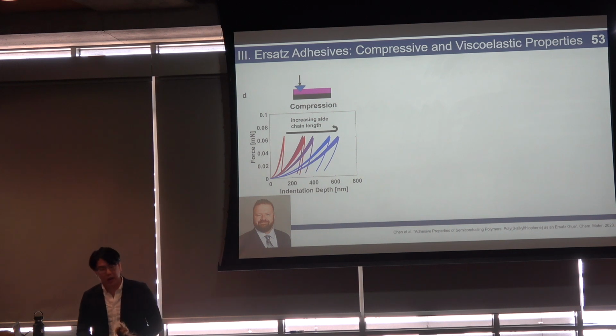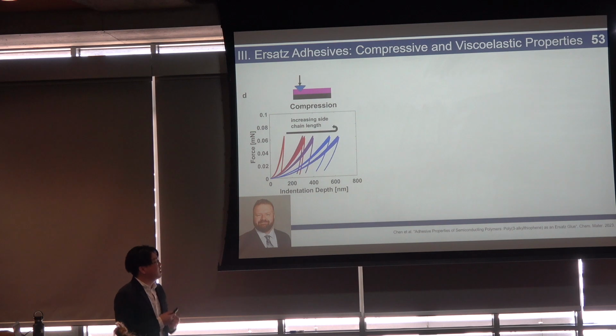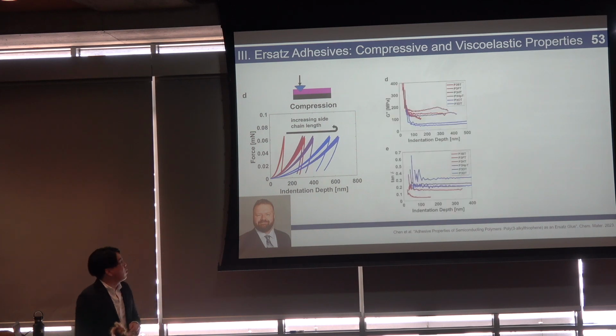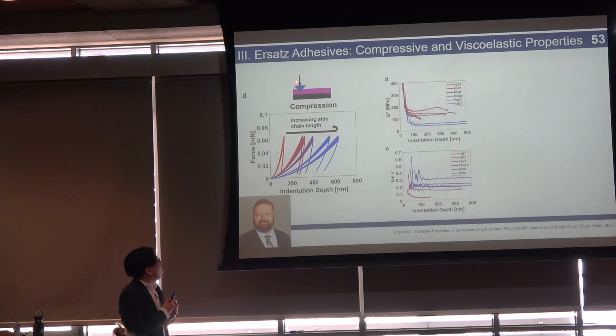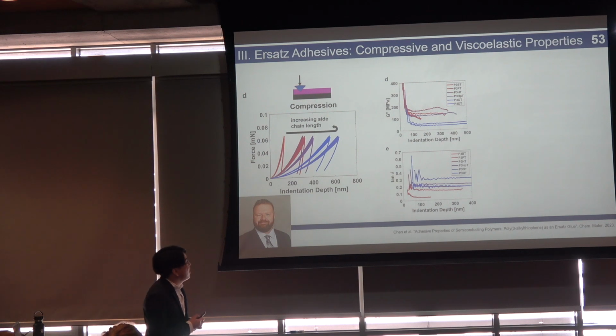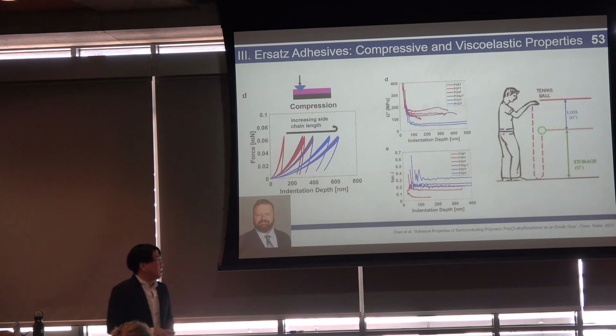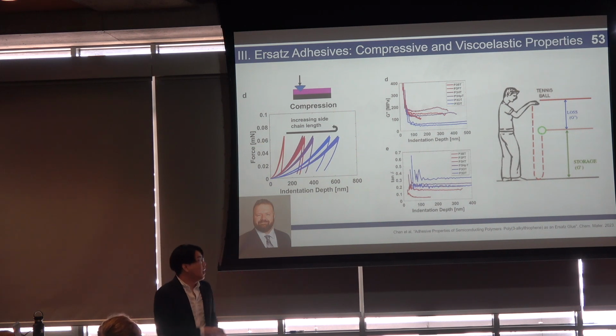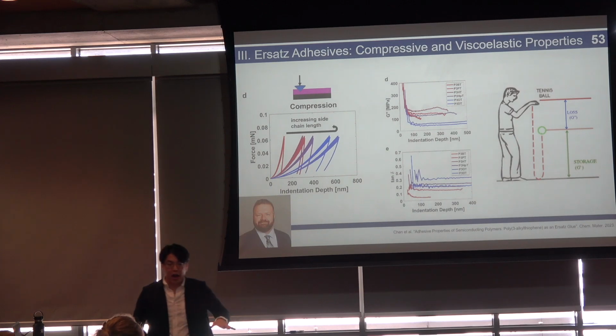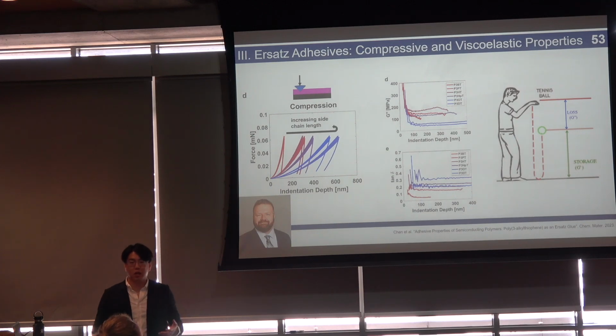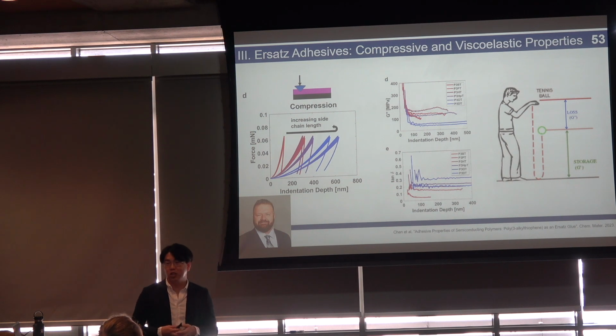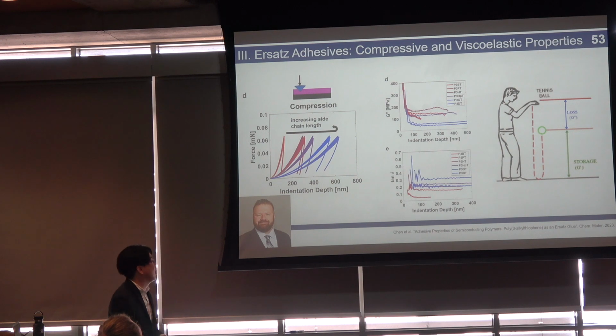So we used nanoindentation to compress these films and measure the mechanical properties. And while you're doing nanoindentation, you can actually oscillate this indenter, and from there you can extract the loss modulus, the storage modulus, and the tan delta. And you can think of these as, for example, if you drop a tennis ball from a certain height and it ricochets back up, the amount of the height that it returns to is basically the energy that was stored. And the difference between the starting height and the final height is the energy that was lost from heat or friction or anything else.